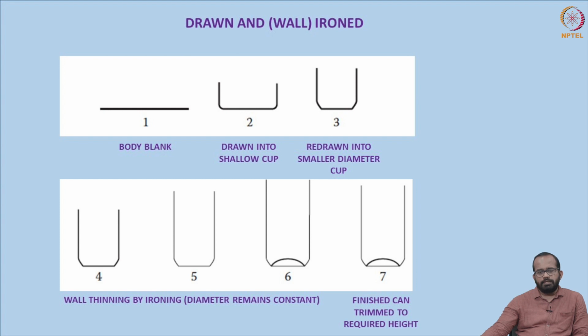In the case of wall ironing, a synthetic lubricant is applied which is washed later, because for ironing the wall, the process has to be really smooth and flawless. Metals are pressed through rollers, or certain dies are used to reduce the thickness of the metal. Normally, metal friction can happen, which may result in the destruction of the metal surface area. So, in order to prevent that, a synthetic lubricant is added in the case of wall ironing. Mostly all beverage cans are prepared using the drawn and wall ironing process, or DWI process, and the food cans use the DRD process.